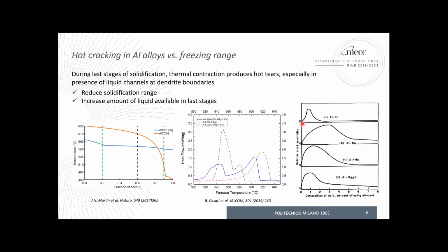It shows that when we go with aluminum and silicon alloys, usually pure aluminum can be processed quite easily, no cracks. There is a critical range of silicon that produces cracks, but if we increase the amount of silicon, such as in these 7%, 10%, 12% silicon alloys, there are no cracks anymore. We induce lots of eutectic constituents.